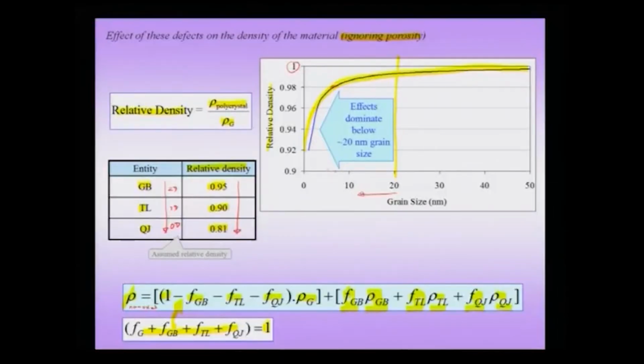Therefore, now I have a polycrystal, what you might call a porosity free or an artifact free polycrystal, purely from the internal geometric structure which involves grain boundaries. There is a reduction in the relative density, and this relative density reduction can be pretty high if I am going to smaller and smaller sizes.